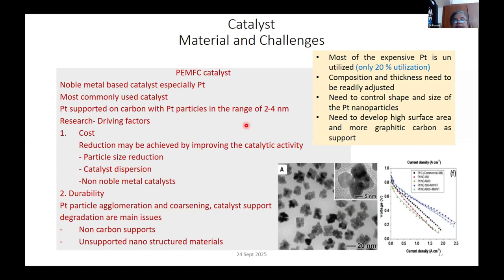And again, like I said, how do you reduce the cost? You can achieve it by improving the catalytic activity. For that, you can do particle size reduction of the platinum, like from 20 nanometers, 10 nanometers, and if you go to 2 to 4 nanometers, you can get better activity. Or you can work on the dispersion in the slurry before making the electrode. That also makes a lot of difference in the performance you get.